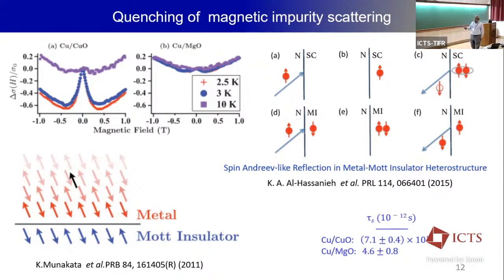But when you bring a normal metal close to a Mott insulator, a similar kind of situation happens. Either the spin will get reflected without any spin flip scattering, or it will form an intermediate state, and finally there will be a spin flip and the spin will get reflected, and there will be a change in delta Sz: the magnetization on the Mott insulator side will increase by delta Sz equal to 1. Because of this, the spin polarization occurring on the metallic side is the natural outcome of this spin Andreev-like reflection.